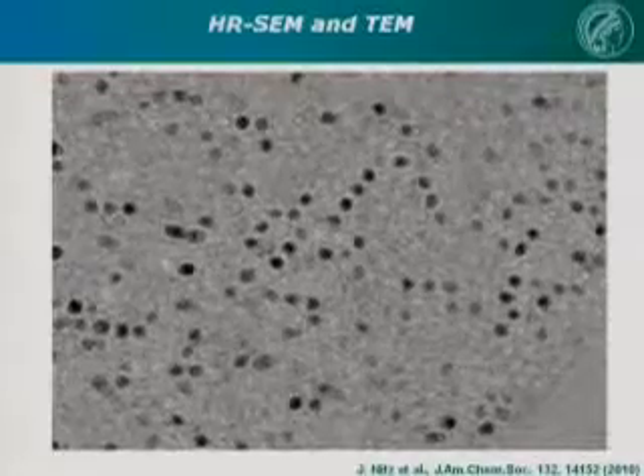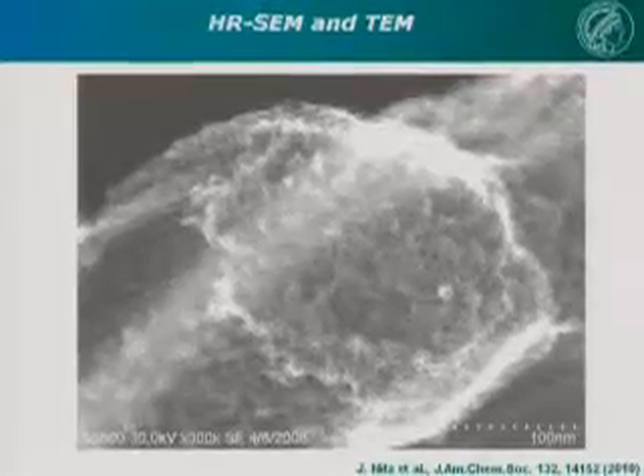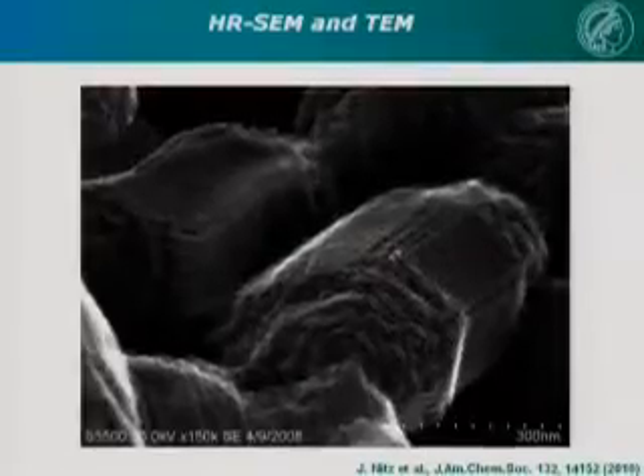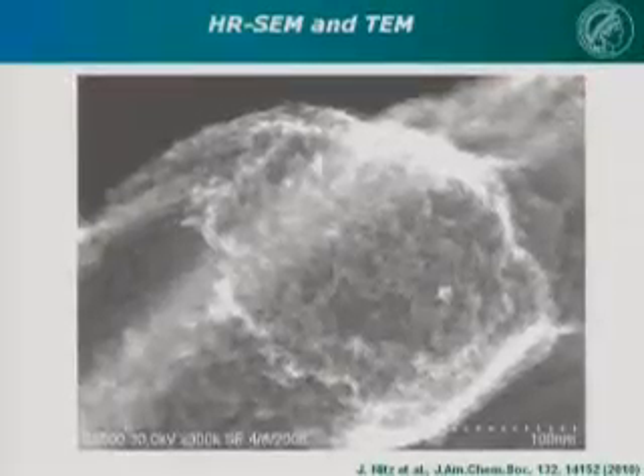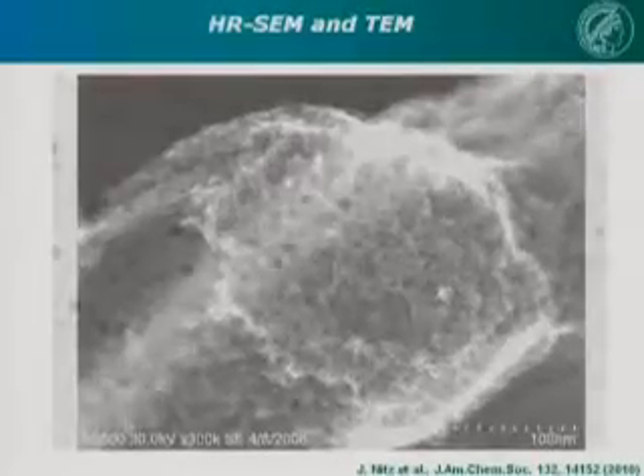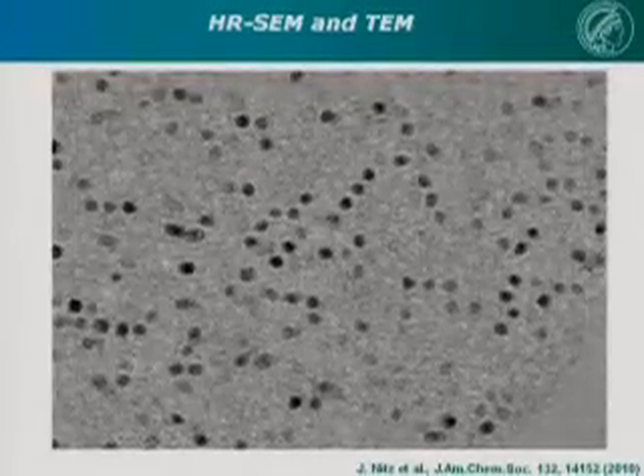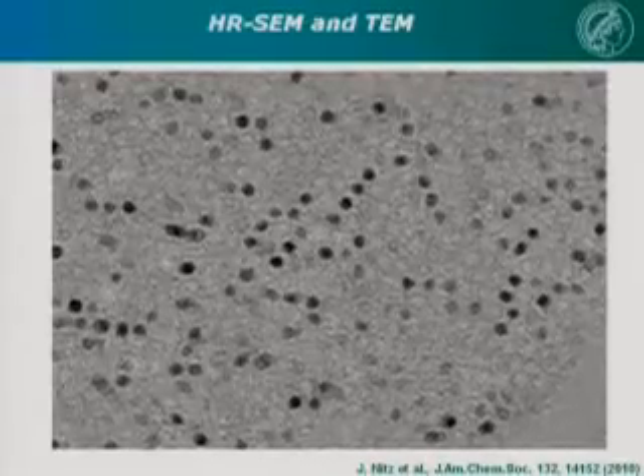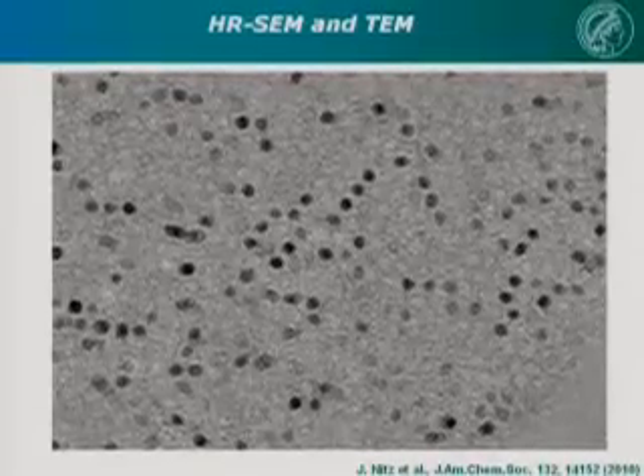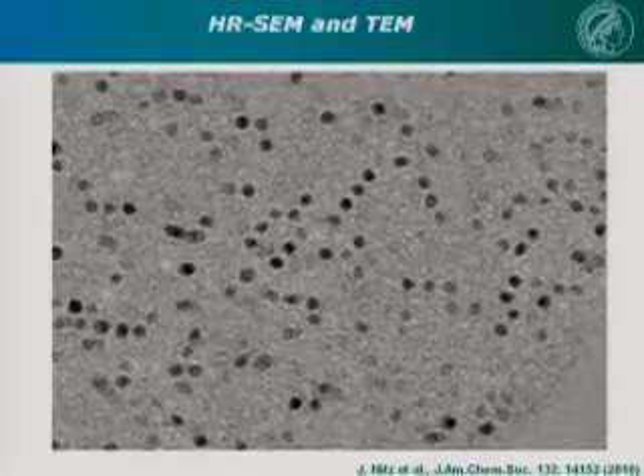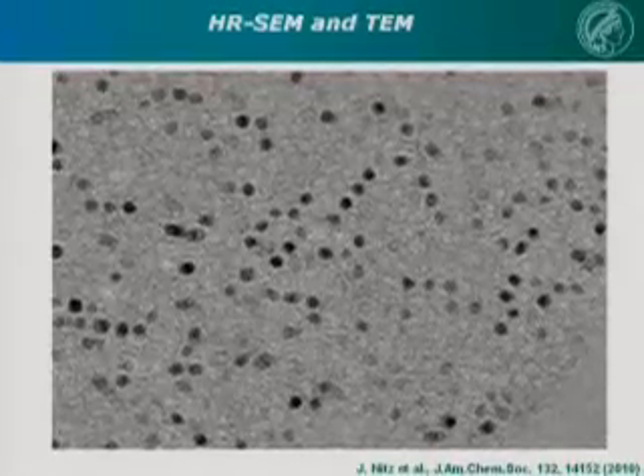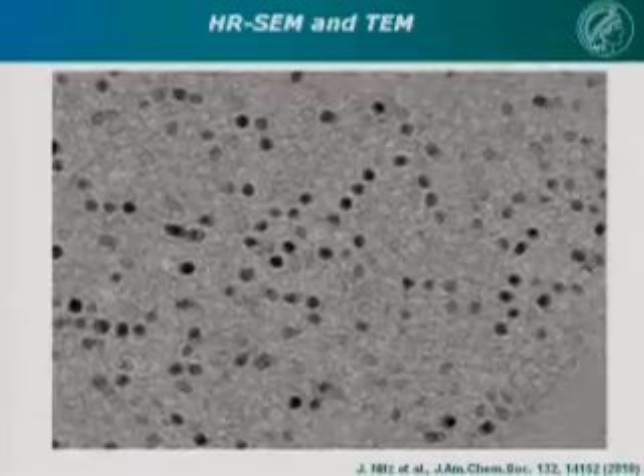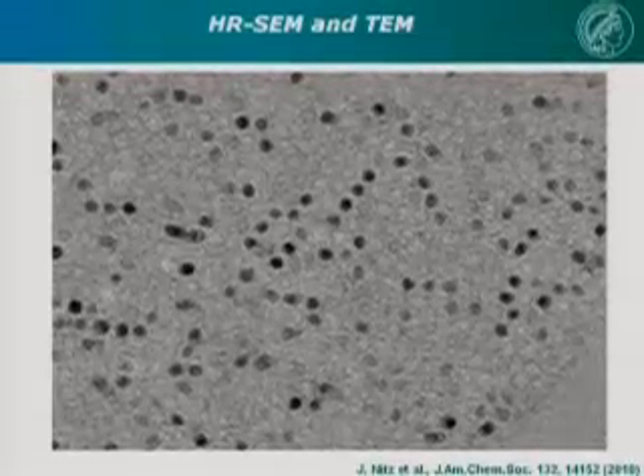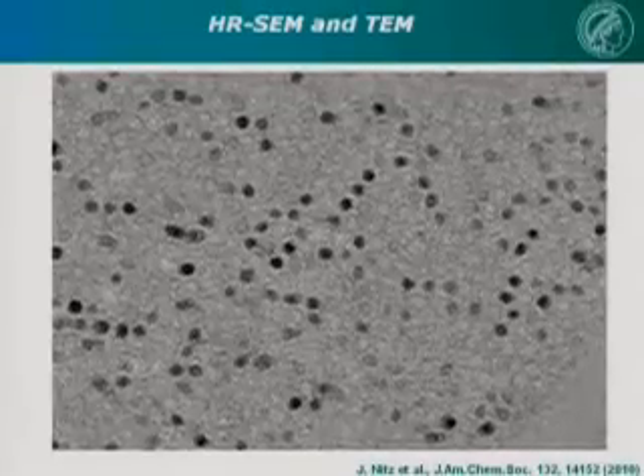You can see that, and now this is transmission electron microscopy, when you cut it perpendicular, so if you cut it through here and then look perpendicular on the sample, then you see basically all these iron oxide particles. Here are 3 adjacent channels, each filled with an iron oxide particle. So here you see an empty channel. It's difficult to see in this image, but they're all the same size, all 4 nanometers, fixed in the channel where we have placed them at will.